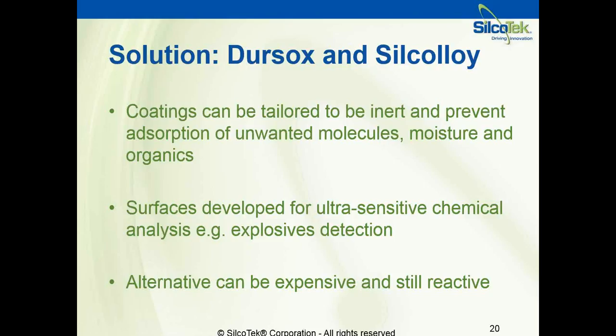So the scientists needed a way to see even to the part per trillion level certain analytes within the matrix that they were analyzing. And with a bare stainless steel substrate, which is extremely common for many instruments, from the injector site through the fittings and valves and tubing, those are all sites for important molecules to stick. And they found that with the coating, those molecules completely traveled to the detector, and there was almost no absorption whatsoever, and they get very, very high response compared to an untreated surface.